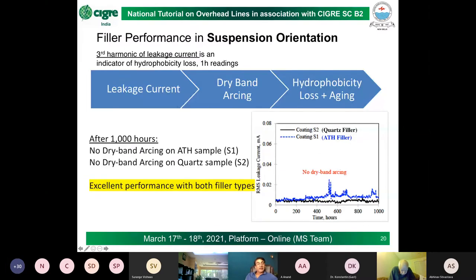We know that leakage current causes dry band arcing, which causes hydrophobicity loss, which is essentially aging and pushing the coating to end of life. So this leakage current is a bad idea. It's the enemy of the coating, of silicones actually, especially in this context. For all kinds of coating, quartz fillers, ATH fillers, in the suspension, vertical orientation, there has been almost no difference in performance. Everything works really beautifully, all is well.